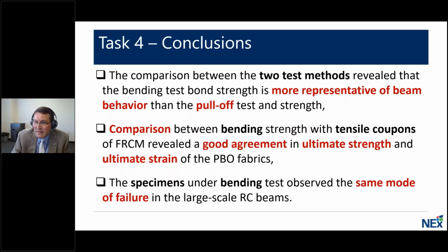In terms of the two test methods, it revealed that the bending beam test is more representative of bending beam behavior than the pull-off test. Comparing the bending strength with tensile coupons of FRCM revealed a good agreement in the ultimate strength and ultimate strain of the PBO fabrics. So the beam test worked best there. Also, the beam test resulted in the same mode of failure as we saw in the larger scaled reinforced concrete beam tests. So that was also a very important correlation between the two.